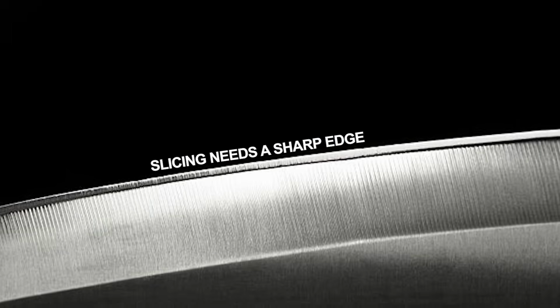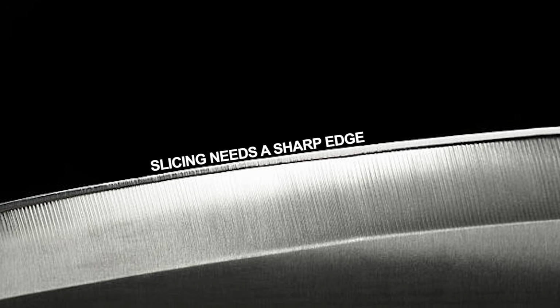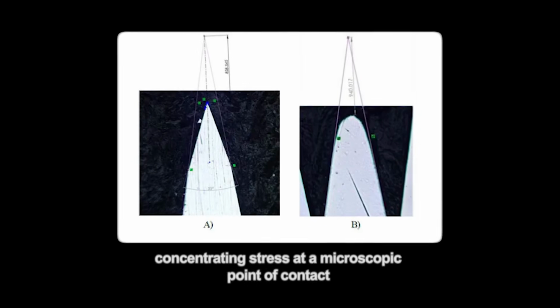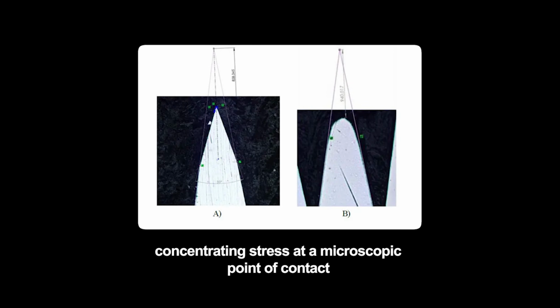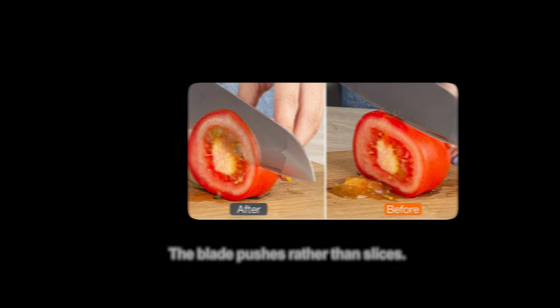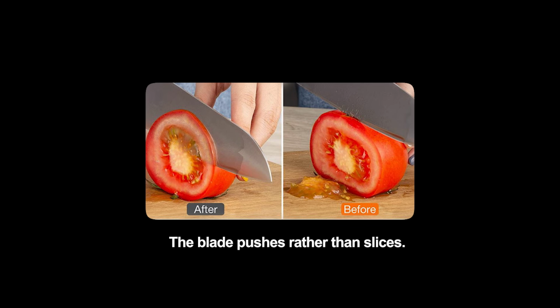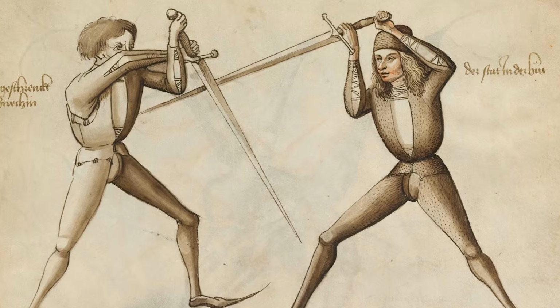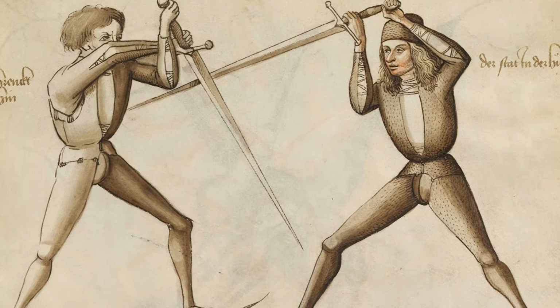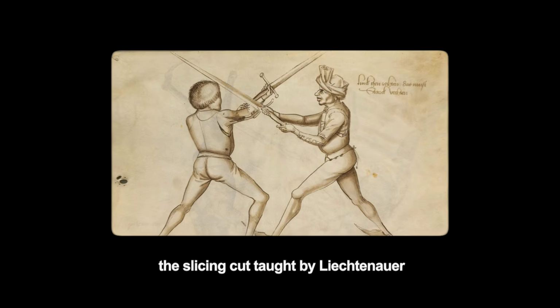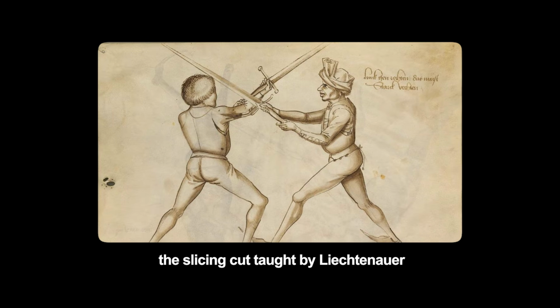The physics of slicing require the edge to initiate a cut by concentrating stress at a microscopic point of contact. Widen that point through dulling, and the stress distributes across a larger area. The cut doesn't initiate. The blade pushes rather than slices. The fencing manuals care deeply about this. Techniques like the Abschneiden, the slicing cut taught by Lichtenauer, work by pulling the edge across a target after initial contact. This multiplies the cutting effect beyond what a single chop could achieve.